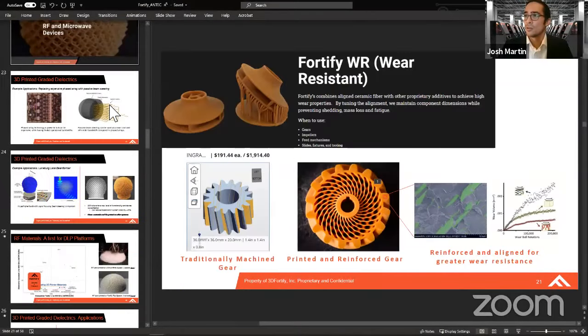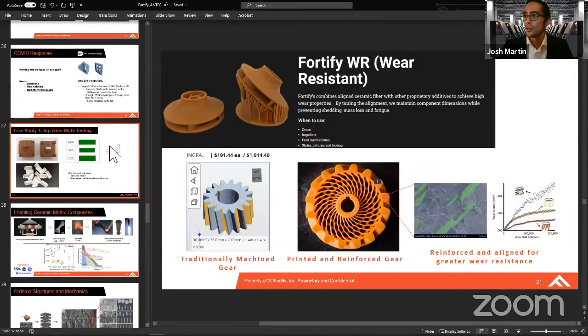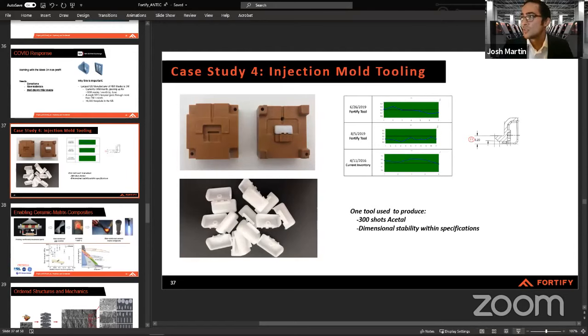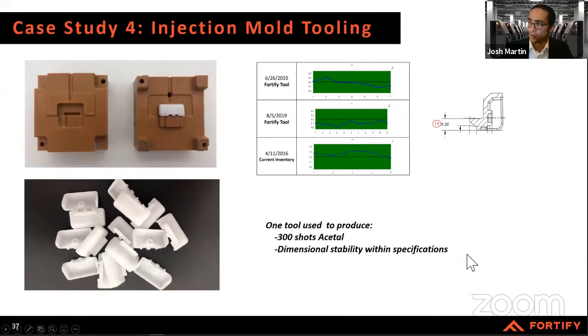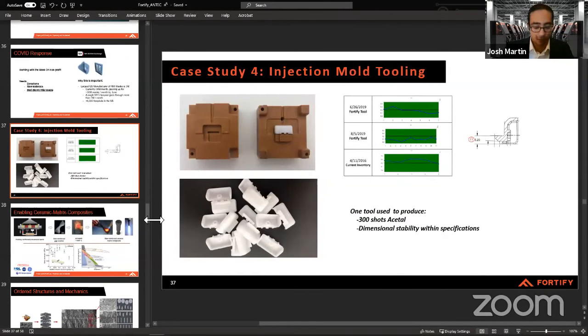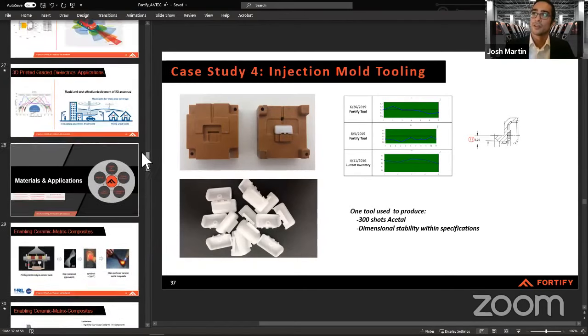And let me just show something back here. In regards to using soft tooling, we did some work with TTH out of Ohio. They've molded, it's actually over 300 shots of this acetal blend. They found that these tools were able to maintain their dimensional tolerance within the same scope as their metal tools. So that's something that we're excited about. Reinforcing these resins means that we're getting lower CTE, we're getting higher heat deflection temperature. These tools are just more robust and able to maintain their tolerance.